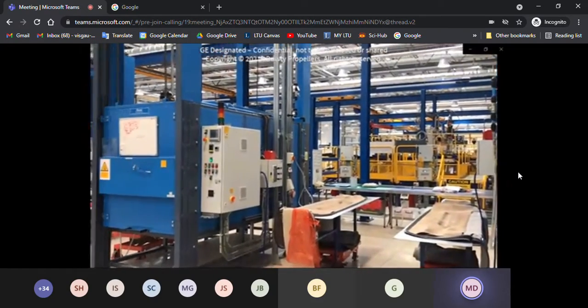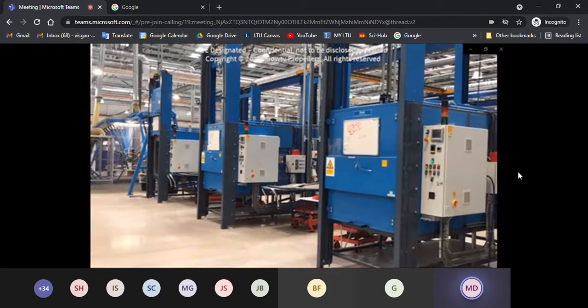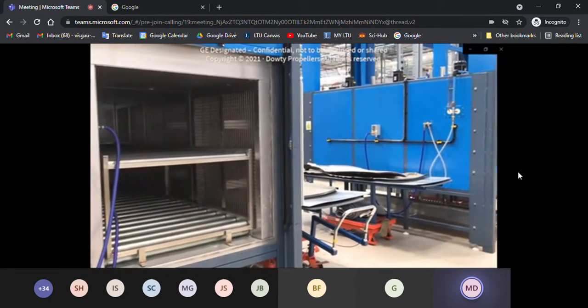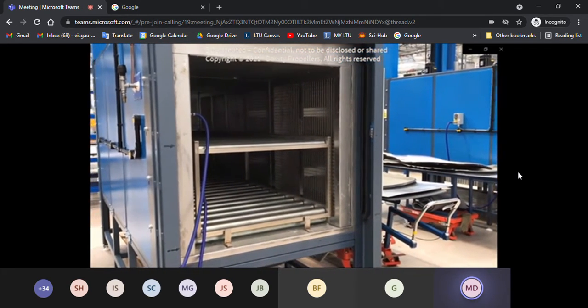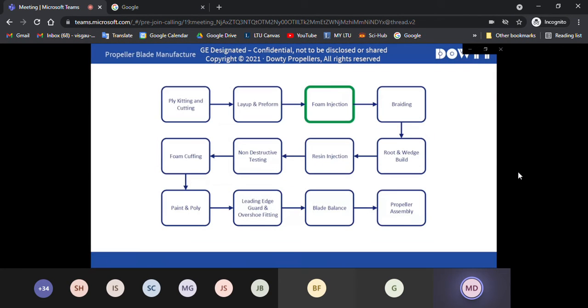After layup of a blade preform, the preform is transferred to a vacuum bag where vacuum is applied, and the vacuum bag is then placed into an oven to consolidate the preform ready for the next operation. There are 2 preforms per blade, one for each face, and they get combined the next operation to form what begins to look like a propeller blade. And that next operation is foam injection, where we take the 2 preforms, one for each face, put them together into a mold and inject foam into the center.